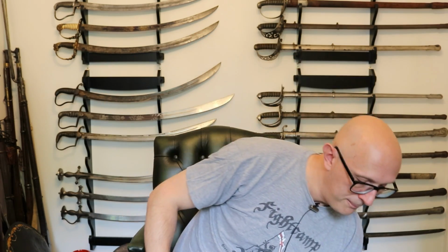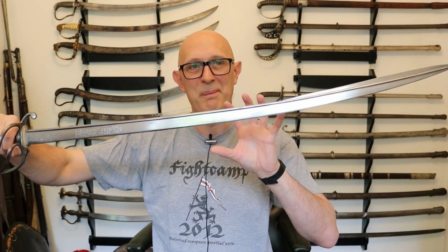A European sword edge, if I go to this sabre, so by the time we get to monosteel blades in the 19th century, this will be around 50 Rockwell at the edge, so it's now harder because they can get it harder with less risk, partly because of the technology. They're better at heat treating things by that point, but also this is monosteel, so it's got less rubbish in the blade essentially. This is essentially a crucible or cast steel as they called it.